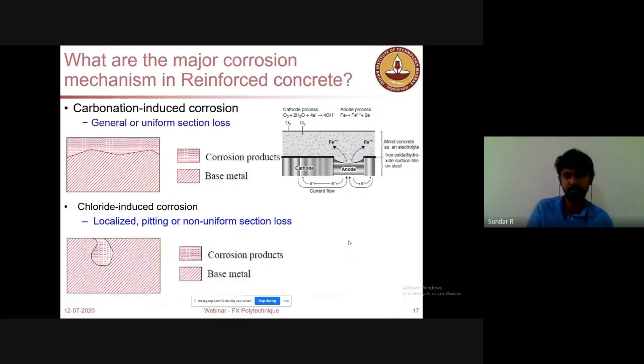There are two processes by which corrosion can happen: carbonation-induced corrosion as well as chloride-induced corrosion. The carbonation-induced corrosion is primarily due to the reaction of atmospheric CO2 with the cement phases. Due to that, there will be a reduction in the alkalinity, and because of that, there will be corrosion that is uniform in the process. If you consider carbonation-induced corrosion, the steel will be corroded uniformly throughout the cross section of the concrete member. But when you go for chloride-induced corrosion, the failure will be a localized one.